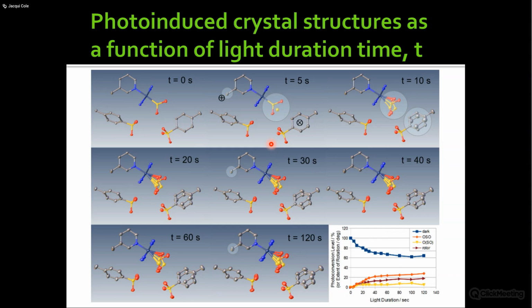One of the things that has attracted our attention is exactly what the mechanism behind this light induction process is, structurally. I've hinted at that in the introductory cartoon of what's happening, but this is really our experiment where we tried to prove what was happening in terms of the mechanism. Every case is slightly different, but this is a general trend that we see, as a representative example. We did this on the 3-methyl pyridine with the trans ligand. Now I'm going to show you a collation of many different full crystal structure determinations.